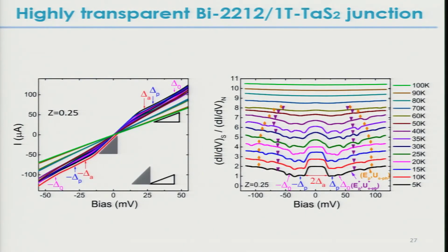Here's again just the current voltage characteristic. You can easily see the doubling of the conductance, this is for a Z of 0.25, or a high transparent junction. And this is the normal state. So these are different temperatures. And we can do a lot of spectroscopy, which we've done. This tunneling spectroscopy is the differential conductance, superconducting normalized to normal state.